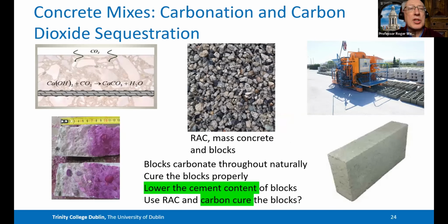A lot has been said about concrete sequestration, and we need to be very careful there because we have to design our reinforced concrete structures so that we don't sequestrate carbon dioxide. And the reason for that is that if carbon dioxide makes its way into concrete, the concrete is sufficiently permeable and has a fast diffusion rate. Within its lifespan time, in the presence of oxygen and water, we are going to cause and will cause and do cause serious corrosion of reinforced concrete. So we design it so that it only permeates within its life to maybe 20 or 30 millimeters.